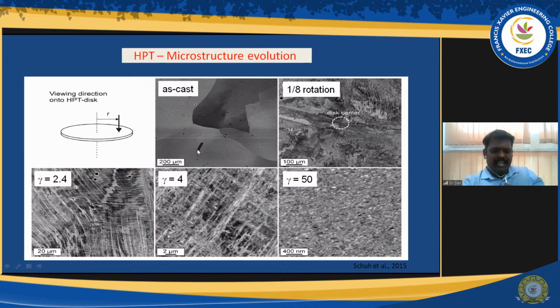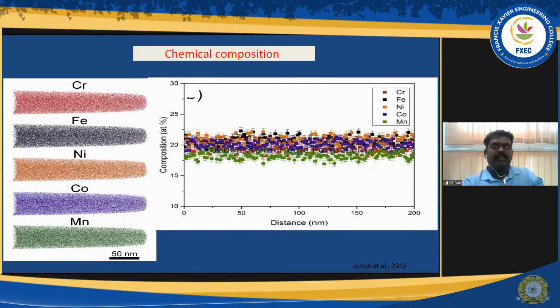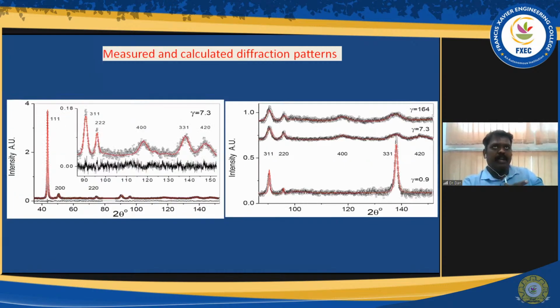I will try to explain what they tried to do. They tried to refine this material from the as-cast structure. In the as-cast state, you can see a very large grain size. After refinement, clearly you can see the number of turns. I told you that with an increasing number of turns, the refinement will increase, right? With increasing refinement, you can see deformation bands, and finally you can see the subgrain structure. They also looked at the chemical composition at the atomic level. After deformation, these five components are still distributed homogeneously. That's what I wanted to say here.